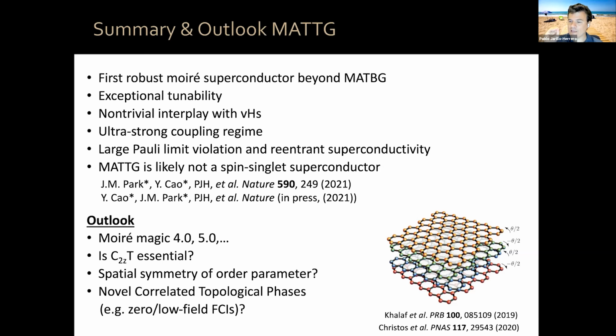Then with respect to the influence of the edges, we do not know yet, and it's a very interesting question. All the theory is always for infinite samples, but all the samples are finite experimentally. So some of the scanning probe techniques have investigated close to the edges. We have not seen in an obvious way a strong effect of the edges, something that would lead us to think that anything in the physics is different. But of course, the moment you have, for example, a quantum anomalous Hall state, you're going to have an insulating bulk and edge states in the system, so you will see edge type of physics, and perhaps what happens at the edge might be relevant, for example, in terms of scattering. You can also realize quantum spin Hall phases here. They may or may not be robust depending on what type of edge scattering you have, etc. So looking at the physics of the edges would be interesting.